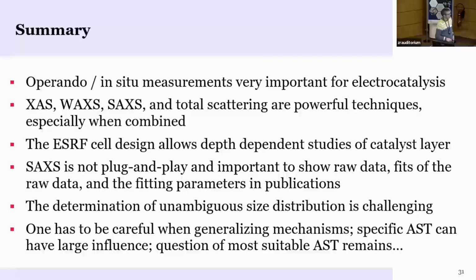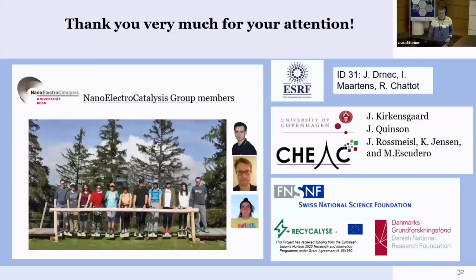And one last thing, these are commercial samples, and what we found is that claiming general effects is always difficult. You take the next catalyst and it looks almost the same and it behaves different. For example, the carbon support is different. So it's very, very difficult to have a general view on degradation, because each sample basically behaves different. So one should be really careful in making general statements. With this, I'd like to thank you for your attention and open for questions.